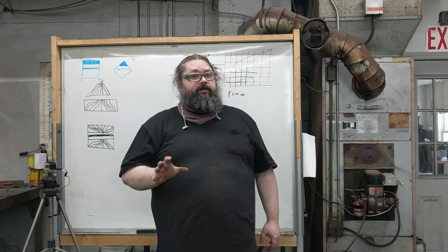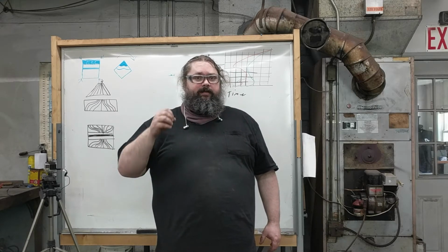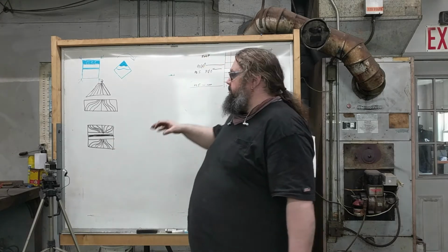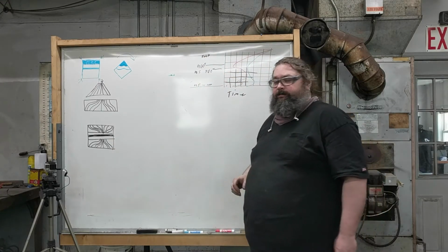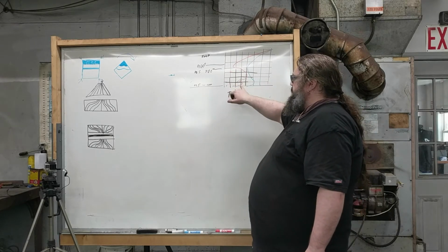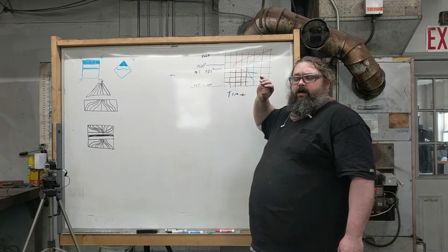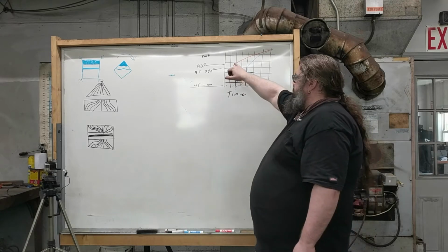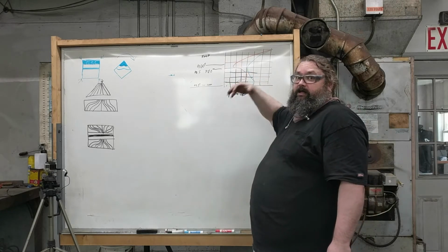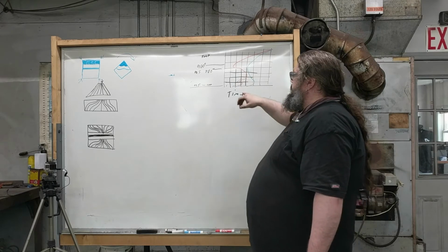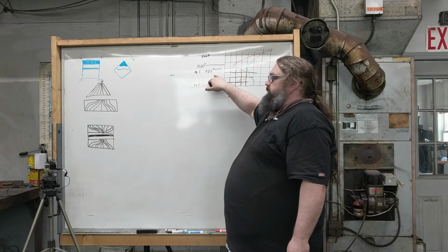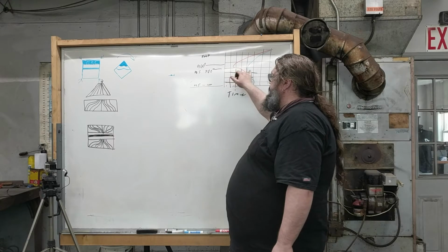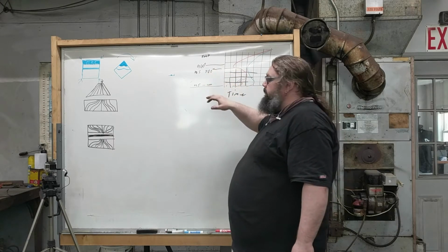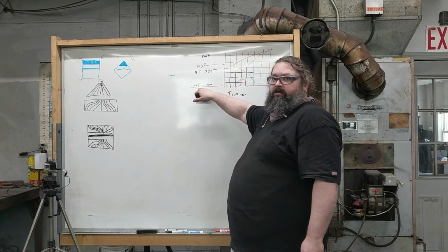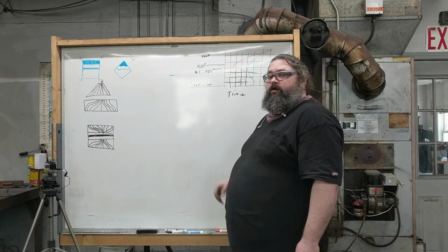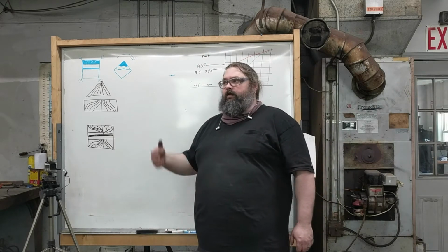Stainless steels are different. Because of the amount of alloy in them and the chemistry involved, what ends up happening is it changes the TTT charts. First thing is you end up with this secondary bump, which is what allows for air hardening. Basically, your pearlite nose gets doubled, so you get a second chance to turn to martensite. The other thing is that the martensite start still ends up somewhere in here, 600-800 degrees. But the martensite finish point ends up down below room temperature, usually significantly below room temperature.